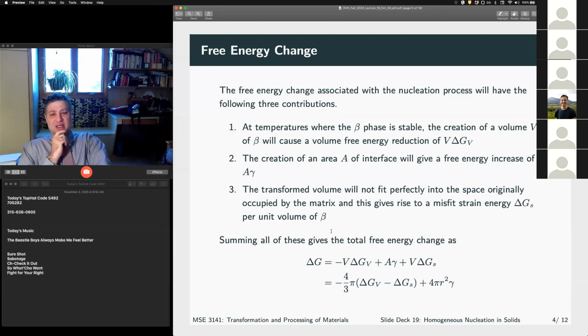so that's going to increase our energy as well. It's usually not phrased as an increase in energy per se, but a decrease in the volume free energy term, sort of for historical reasons, because this is volumetric and this is volumetric, so they get combined together. So here, our volumetric free energy is negative, and our surface energy and our strain terms are positive.